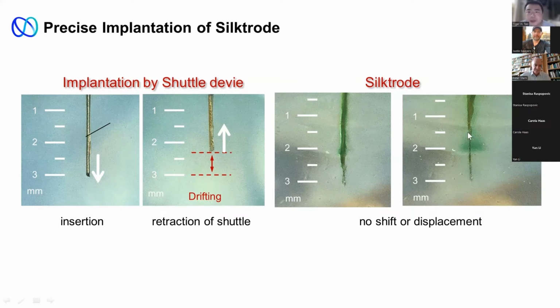But for the Silktrode, because there's no retrieval process at all, after you implant this Silktrode, the coating is going to get dissolved and degrade inside the brain, and the byproduct of the silk is only amino acids. Okay, it's totally safe for the brain, and it won't cause any displacement of those electrodes. So you're going to have a very precise implantation site here. Wherever you implant, it's going to stay there. So that's another advantage you can get from using this very simple strategy.